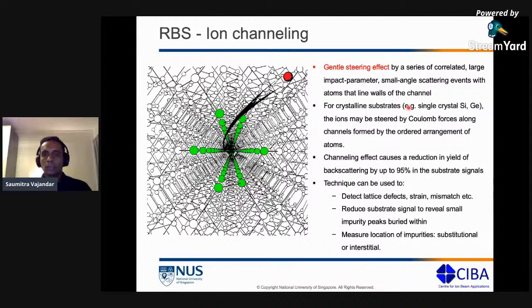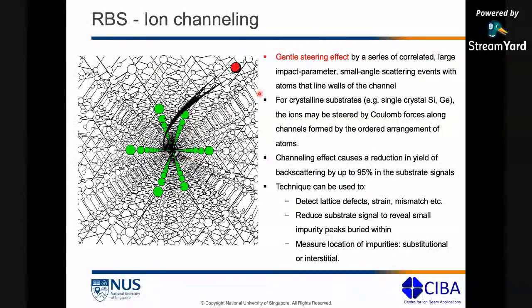Okay. So what are the primary conditions you need if you want to have ion channeling? The first condition is that your substrate has to be crystalline. If you have an amorphous substrate, this doesn't work. If you have an amorphous substrate, this particle will not go into your atomic rows. It'll just backscatter and give you a huge backscattered signal. So the first condition is that you need to have a crystalline substrate. The second condition is that you need to align this channel to your incident ions. If you don't align the channel, you're not going to be able to have this channeling effect, this incident ion going into these atomic rows, right?